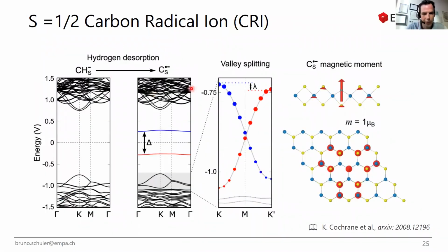Now, doing the calculation, it turns out that the singly occupied defect orbital is spin polarized, and the energy you gain from doing the spin polarized calculation is on the order of about 100 milli-electron volts. So it's quite significant. And that's how the spin looks. There is a small magnetic anisotropy that tries to force the magnetic moment out of plane. So it's very much localized at the carbon center itself. And because you now have a magnetic moment and spin polarized defect states in the valence band, you also see a slight lifting of the degeneracy of your K and K prime valleys as a side effect of having this local magnetic moment.